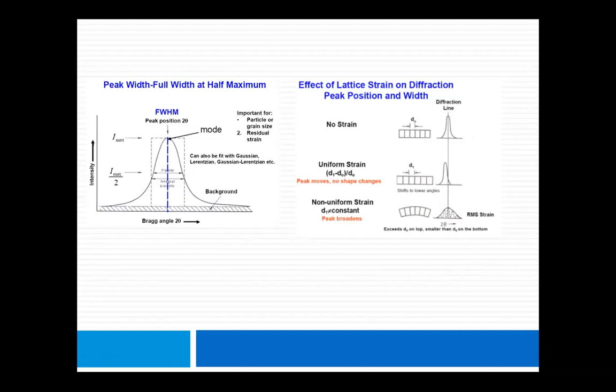If you apply tensile stresses, or tensile stresses are induced, what will happen? D-spacing will be increased, so this peak will be shifted towards the lower side, because 2d sin theta is equal to lambda. Lambda is constant, so when one is changed, the other automatically will be changed. So if both stresses are there, like in a cantilever beam, what will happen? You will get peaks from the compressive stresses on the lower side, because D-spacing is reduced, so theta is on the higher side. If tensile stress is there, D-spacing is increased, so theta will be reduced, on the left side. So compressive stresses and tensile stresses both will shift your peaks to opposite sides, and the crystals which are not under stresses will give their peaks at the original position.